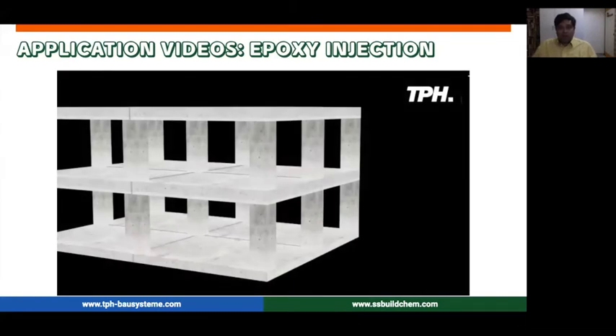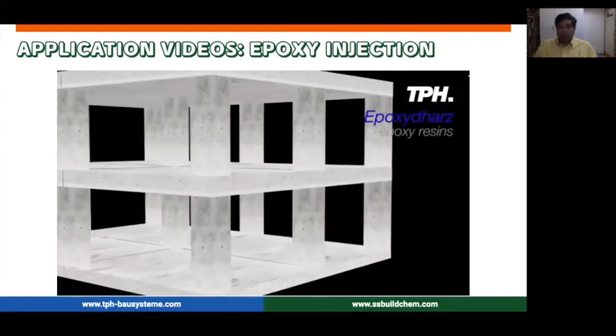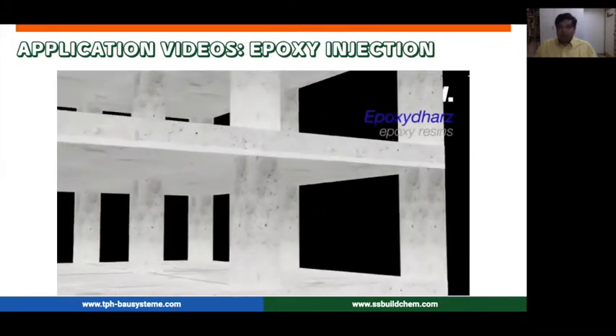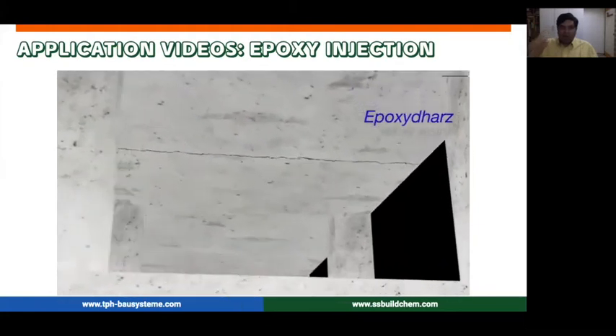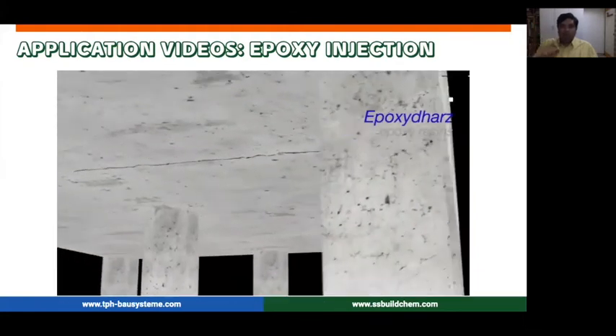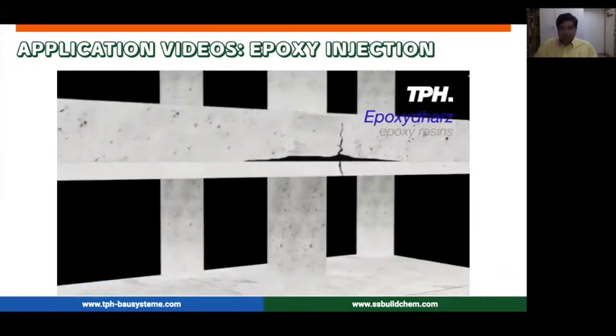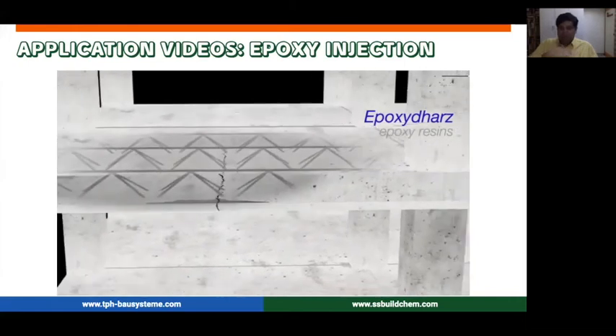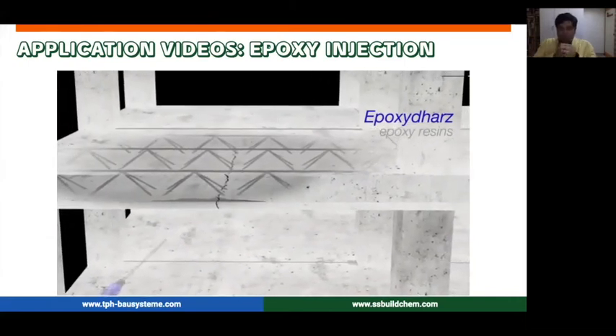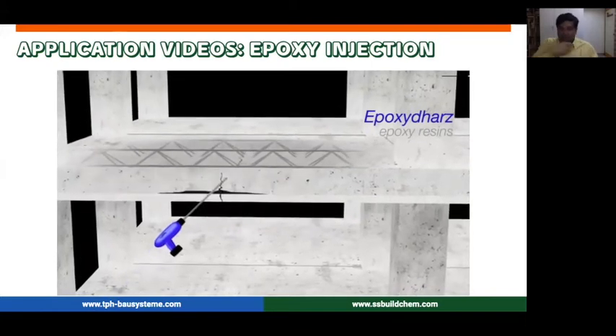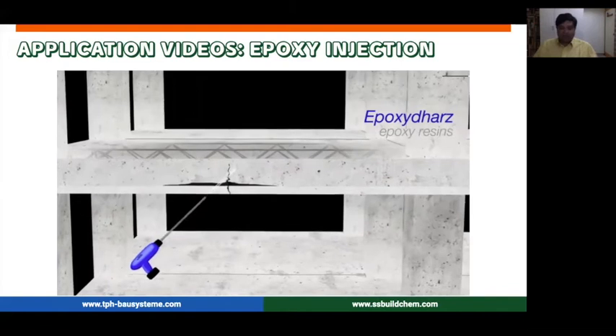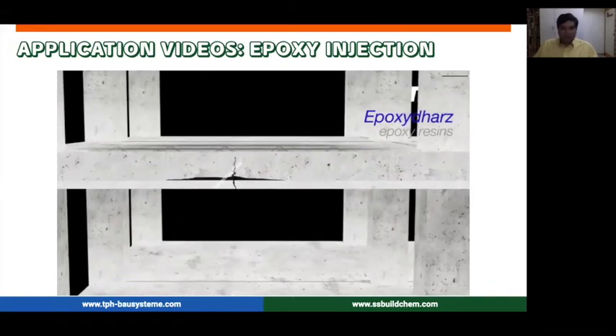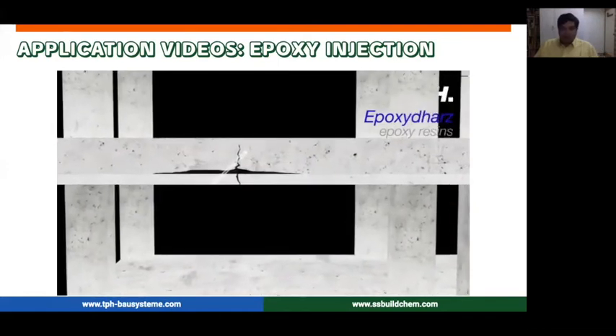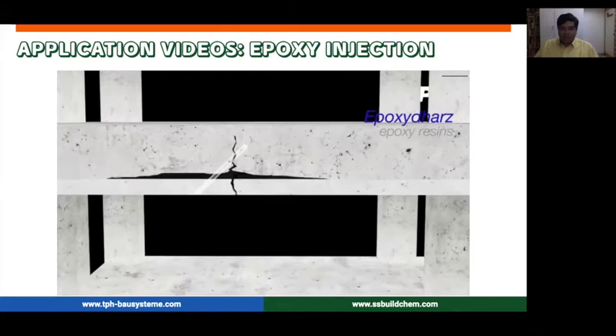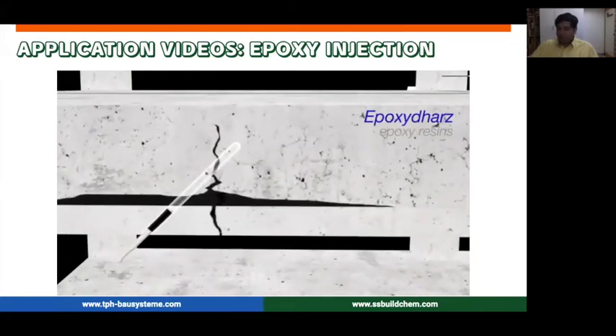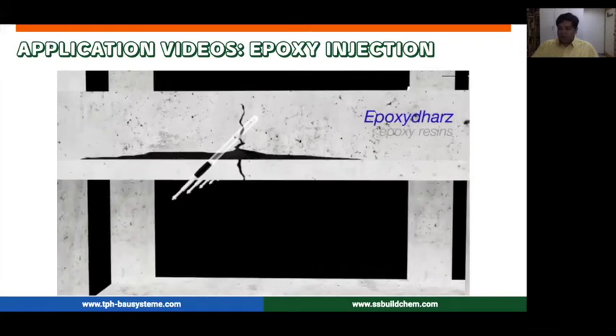For most times, what would be useful, because the load transfer across the cracks needs to be higher, and maybe if the crack sizes are really small, then for 9 cases out of 10, what would solve your problem is a low viscosity epoxy injection. This would help you both fill in the voids, create a homogeneous RCC in that place, and then enable smooth load transfer across your crack face. The procedure more or less remains similar. You just drill across your element and intersect the crack, clean it out, attach your packers, and then continue with the injection system.